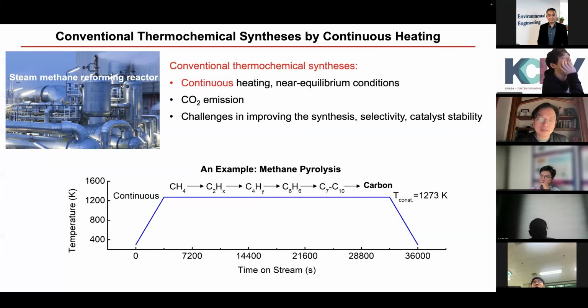So you see this giant chemical plant, and they are using basically conventional fuel, and you heat it up, you turn it on, it's always on. And it's hard to control the kinetics. You say, oops, I changed my mind, I want to stop it, or I want to have this kind of controllability of reaction. For example, in front of you, you have this methane pyrolysis, right? You have one carbon, you have another carbon, you cannot stop it. So in the end of the day, you get carbon black, right? And you get hydrogen. Very often people are interested in hydrogen, and you're trying to deal with carbon black, right?